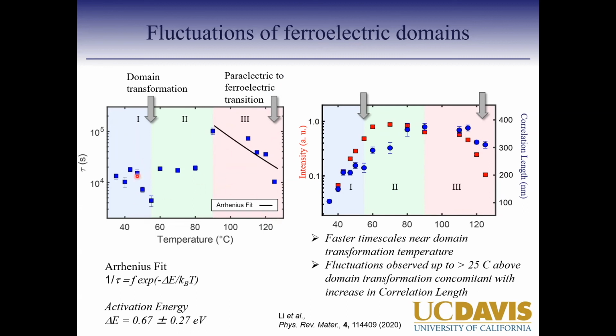However, this one really depends upon how much strain there is. In these films, we think that this domain transition is actually a first order transformation, and so the difference in behavior could really be coming from that. But a bulk system doesn't show this sort of domain structure, so it gets harder to compare how that would look to an actual paraelectric to ferroelectric transition, which is a first order transition in a bulk system.